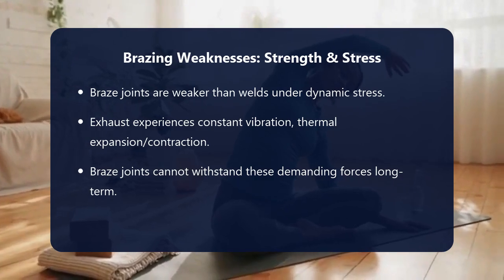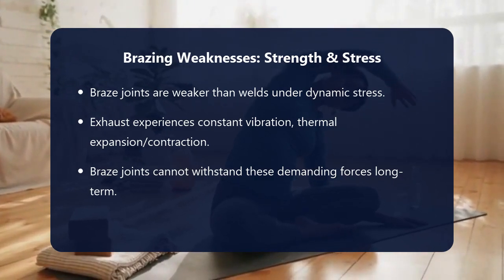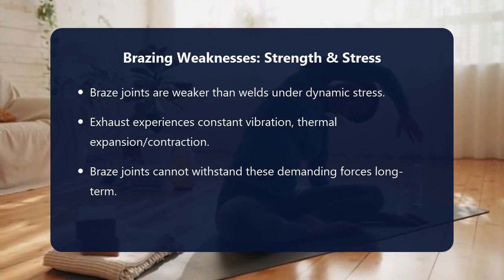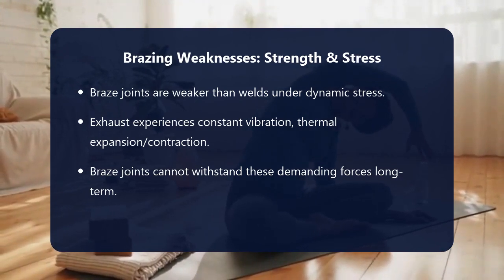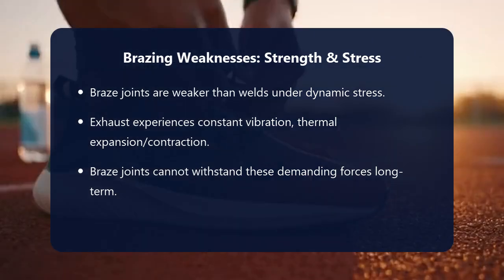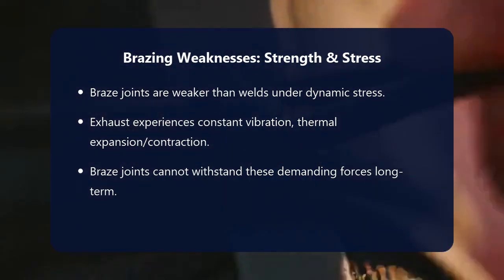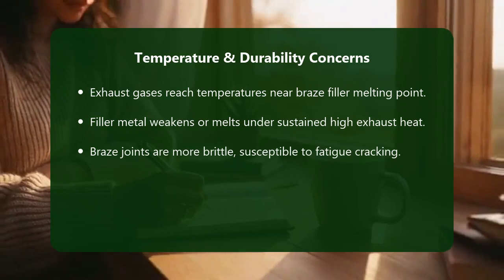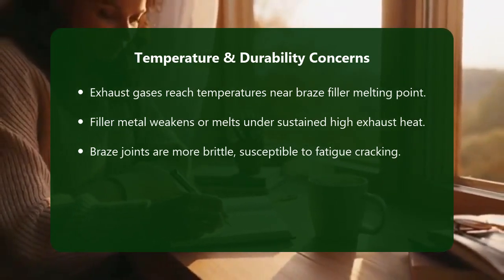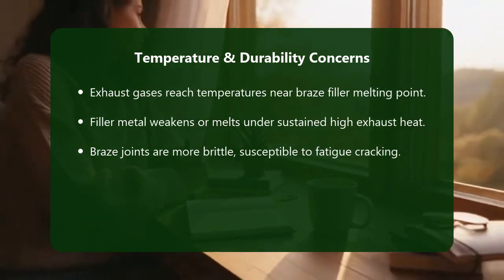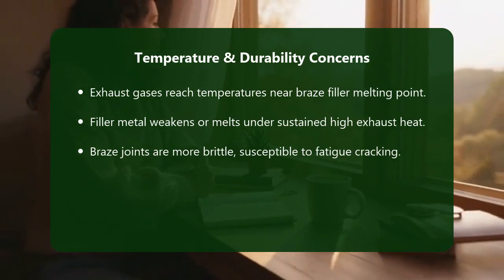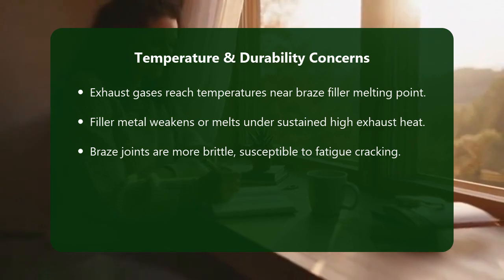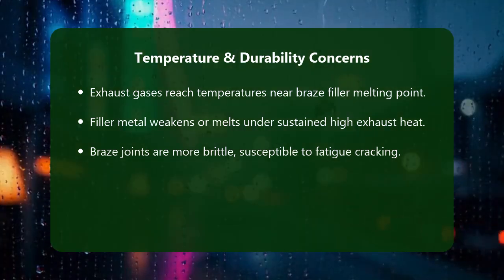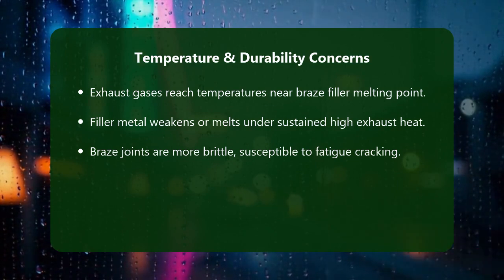Exhaust gases, especially closer to the engine, can reach temperatures well over 1,000 degrees Fahrenheit, 538 degrees Celsius, sometimes even exceeding 1,600 degrees Fahrenheit, 871 degrees Celsius in high-performance applications. Common brass and bronze brazing filler metals have melting points typically in the range of 1,600 to 1,700 degrees Fahrenheit, 871 to 927 degrees Celsius.